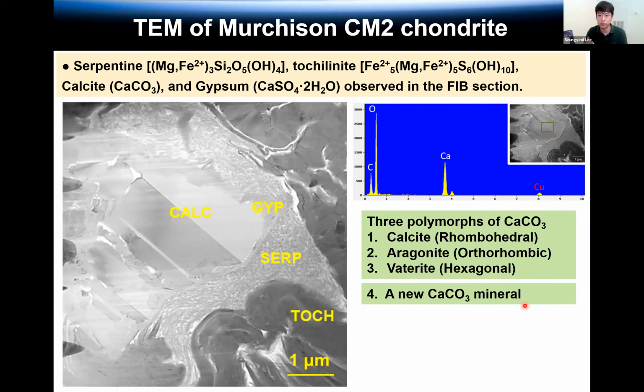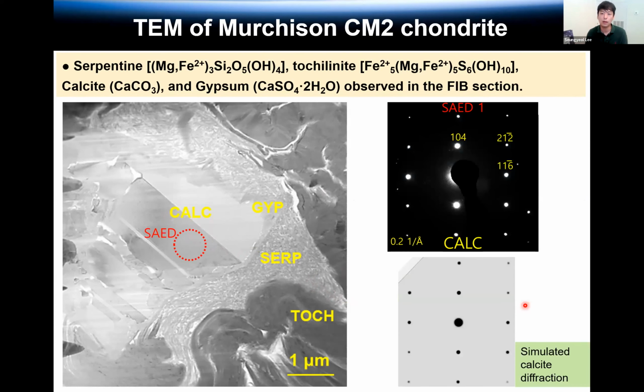So the determination of structure is very important to characterizing minerals. So TEM can provide the selected area electron diffraction pattern. So we can get a diffraction pattern, a different pattern from the sample. So this is a diffraction pattern from this spot, and it also very well matches the simulated calcite electron diffraction pattern. Now we can say, oh, this mineral is a calcite because the chemistry and structure both well match the calcite crystal. Yeah, this is a good example of how to determine the mineral phase in the TEM.